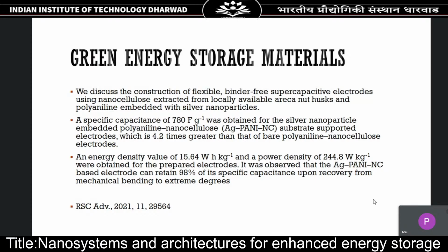So coming to green energy storage materials, what is meant by green? Green means something which is environmentally very friendly, right? One of the recent works carried out was the construction of flexible and binder-free supercapacitive electrodes using nanocellulose extracted from areca nut husks, combined with polyaniline and silver nanoparticles. We got a specific capacitance of 780 farad per gram, an energy density of 15.6 watt hour per kg and a power density of 244 watt per kg. The cycle life is also very good. It could retain up to 98% of its specific capacitance. This was published in RSC Advances.